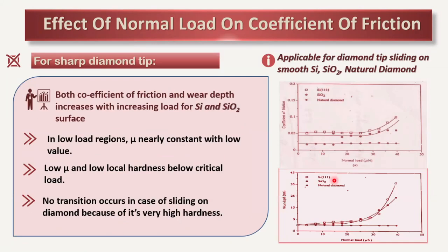These are the curves for sharp diamond tips sliding on smooth silicon, silica, and natural diamond. Both coefficient of friction and wear depth increase with increasing load for silicon and silica, but no transition occurs in the case of the diamond surface because of its very high hardness.